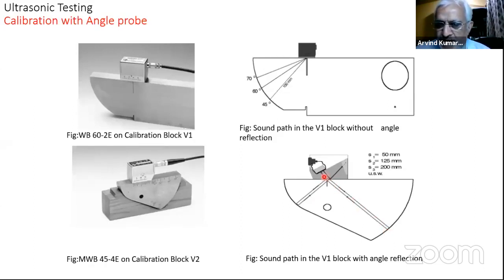So it travels 75 and then again 50. The second peak will come at 50 plus 75, that is 125. The third will come at, again, you keep on adding 75 each time. This is how the multiple peaks come from an angle beam probe on a block with a double curvature. This curvature could be different, like a 25 curvature and a 50 curvature, or a 50 curvature and a 75 curvature. So I should know how the beam is traveling, and based on that, I can use multiple echoes to set a fixed range in my equipment using an angle beam probe.